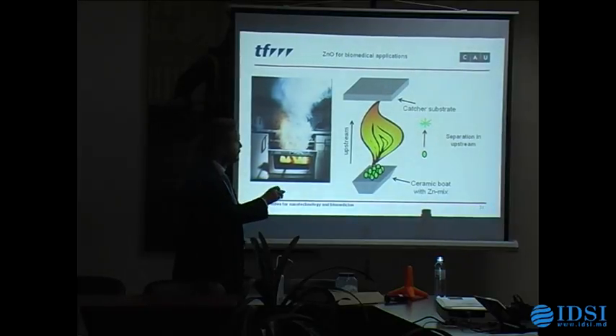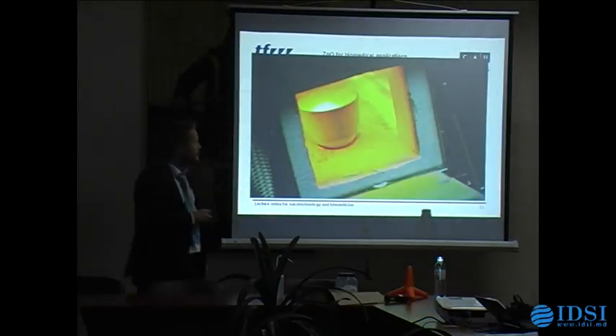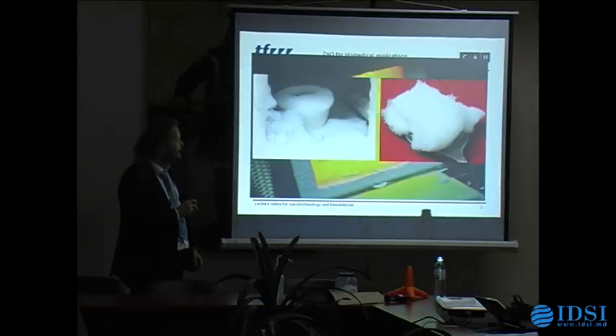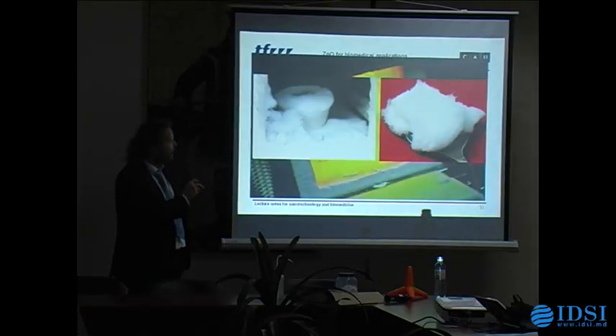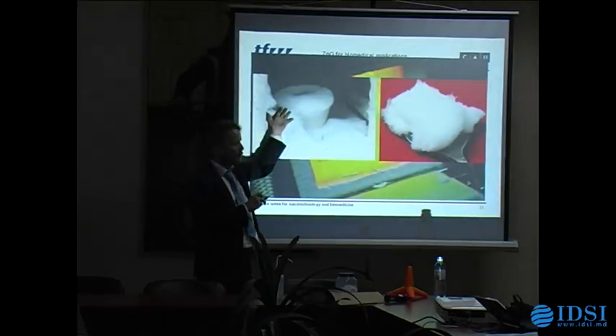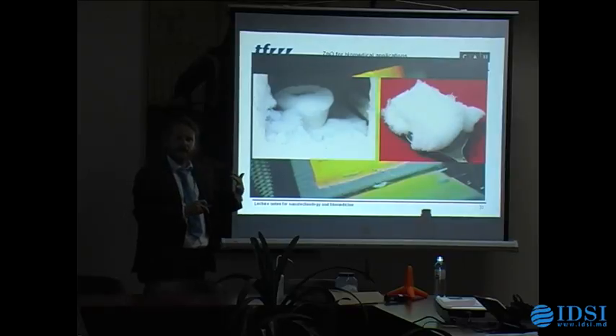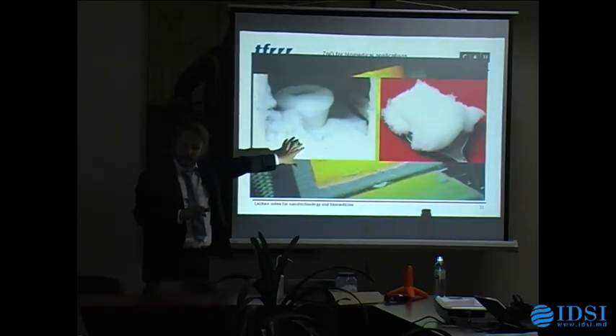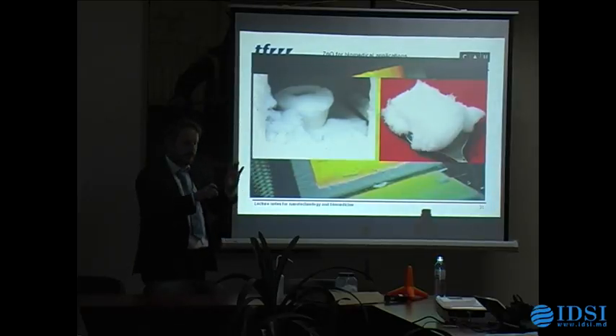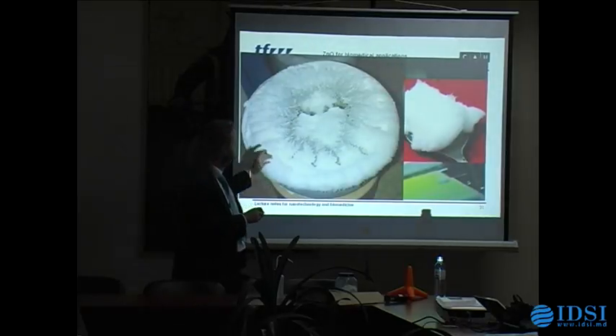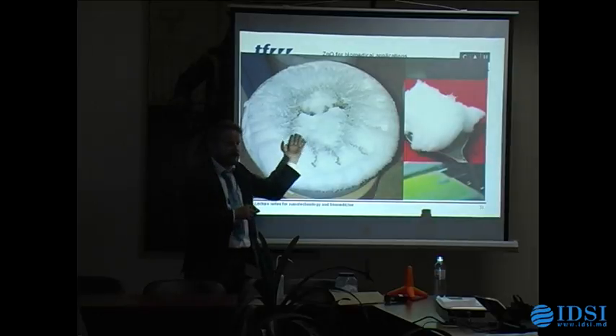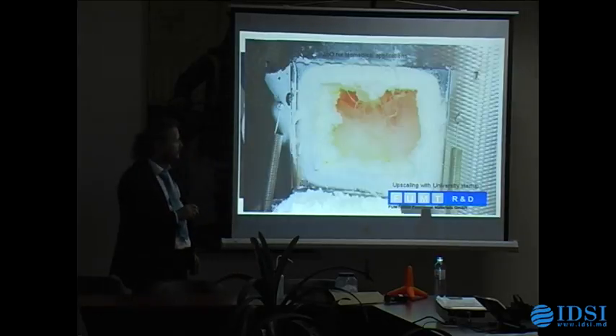So these are separated in the upstream, and now they can be sintered here at the catcher substrate. This is how it looks in reality, and this is how it looks after the synthesis. So you see you get a white powdery substance looking basically like ice, because they're also very polar molecule and transparent originally, but nanostructured. And you can see this here. You can even grow larger crystals here at the top and smaller crystals inside.